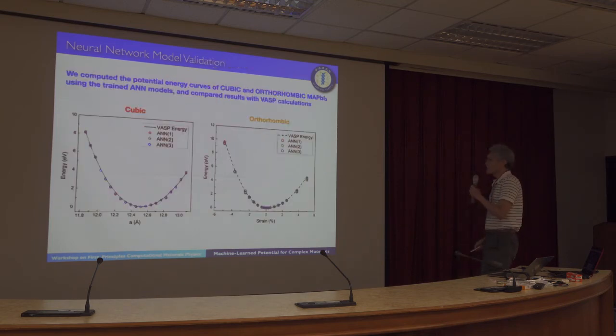And because our training sets were generated using tetragonal perovskite, we also compute the potential energy curves of both cubic and also orthorhombic MAPbI3 using these neural network potential models. And here's the results. This is a different lattice parameter size, and you can find that this is from VASP, and for 3 different models, they almost overlap with those energies from VASP. So this is for cubic perovskite, and this is for orthorhombic. Once again, the agreement is very good.